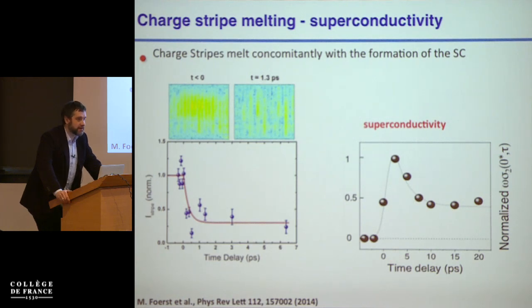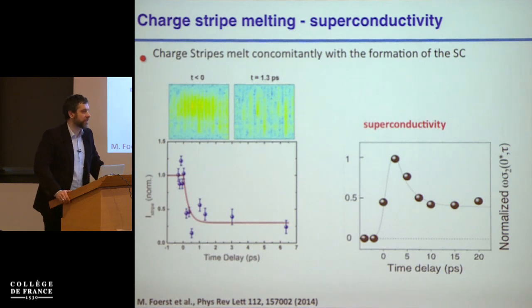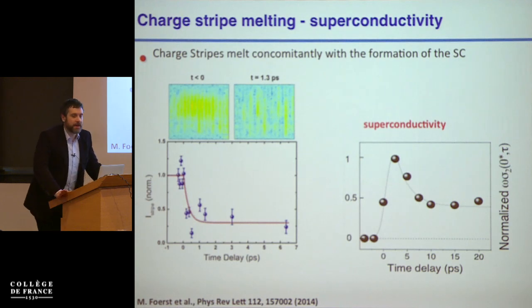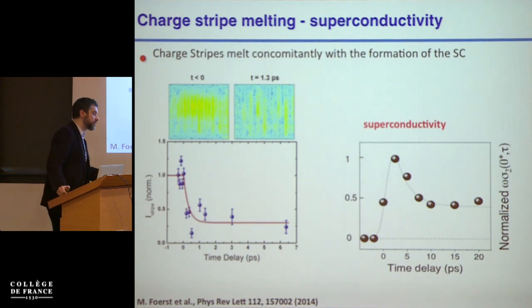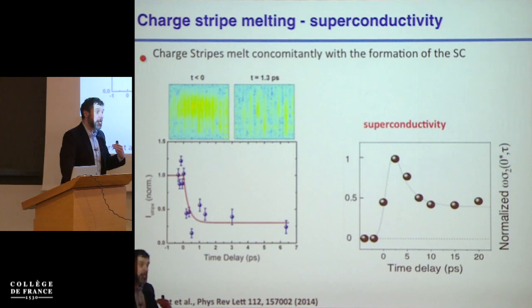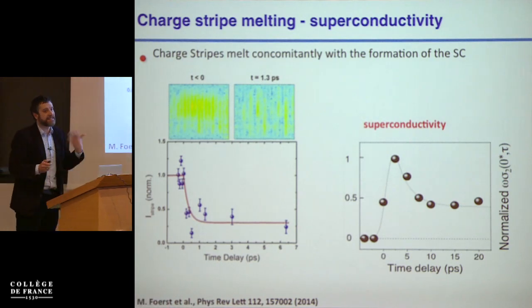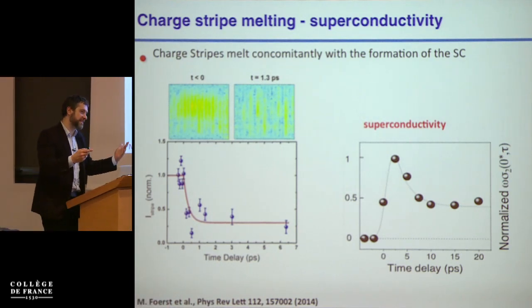LSCO, yes. Right. You mean the zero crossing of epsilon 1? Yes. But that material has an equivalent TC of 35 K at most, right? Yes. So the fact that you can observe this at 80 K is already surprising. Sure, absolutely. Okay, fine. What I'm saying is, it is certainly very surprising, but if you decide that in reality this material has some charge order above TC, and this is depressing superconductivity some,